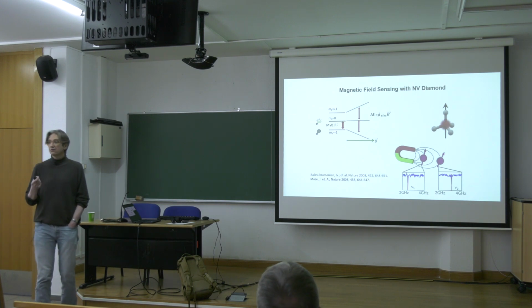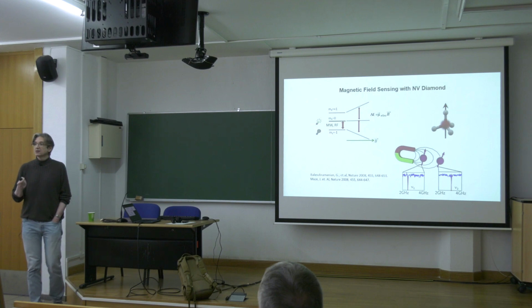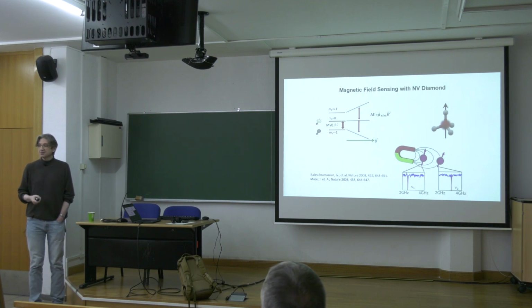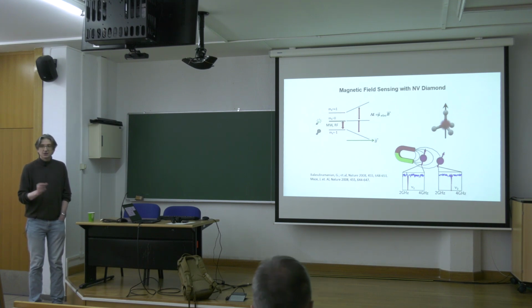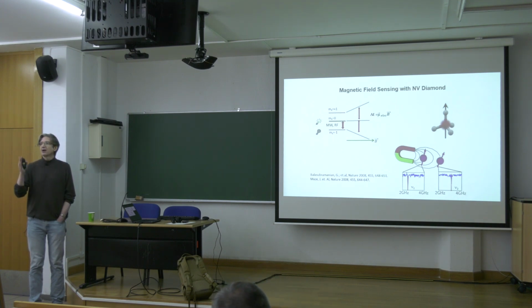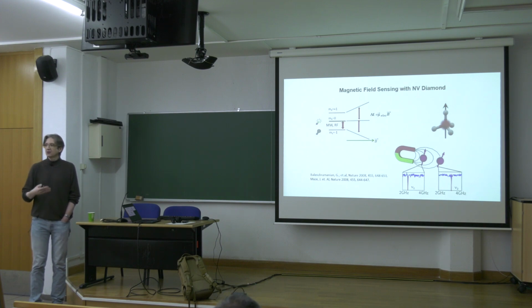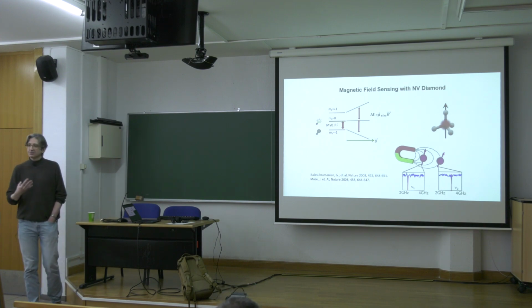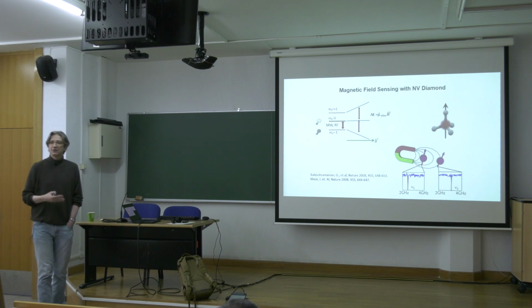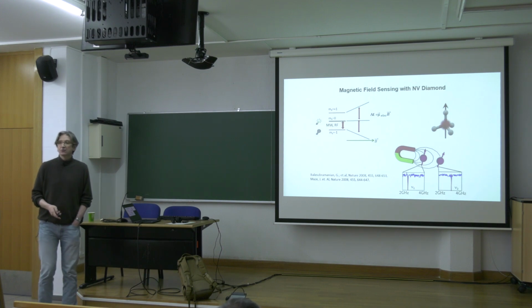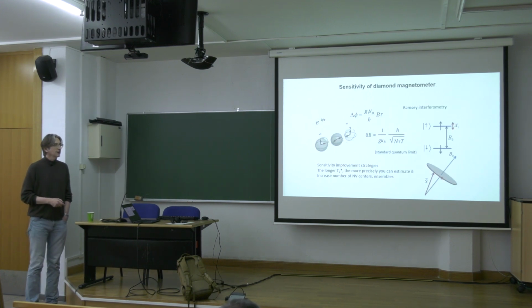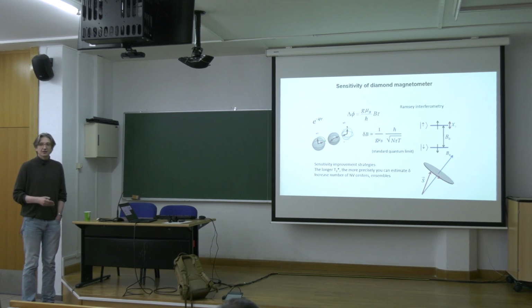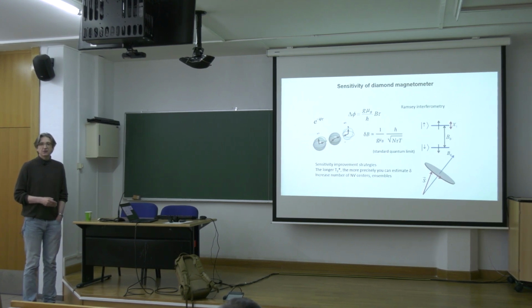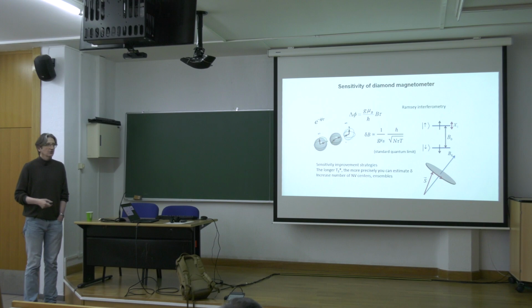Well, the sensitivity of tracking the frequencies is related to the noise present in the system. Here it's photon number, which is always noisy, but also to the width of the transitions. The sharper the transition, the better you can track a frequency. It's very intuitive. You can also put it in a more precise definition of limits, and if you do the analysis, you can get the so-called standard quantum limit or spin shot noise limit in this magnetometry.